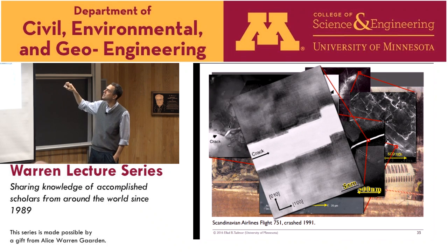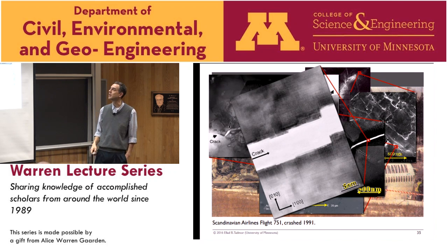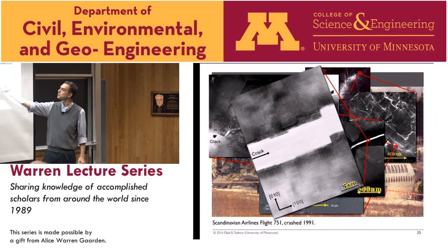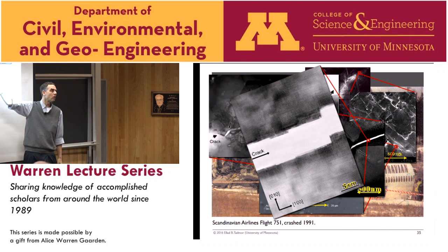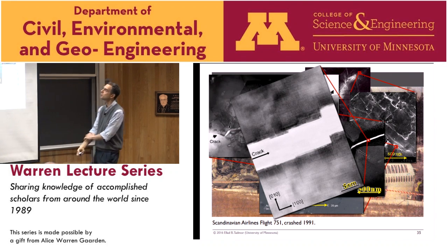As far as this talk is concerned, we've hit the atomic scale. If you can see these dots, this is high resolution TEM, and these dots are atoms or related to atoms, depending how they took this picture. And you can see steps. These are now steps on the surface of the crack that are about 10 atomic levels high or something like that. And now we're at 5 nanometers. So we're all the way down here. Now you could go lower if you wanted. You could go to the electronic levels and so on, but we're stopping at this point.